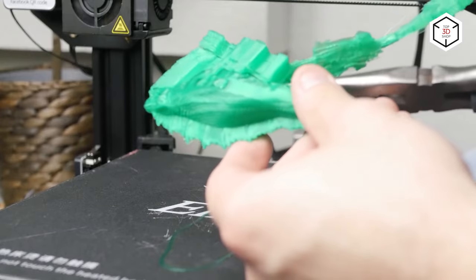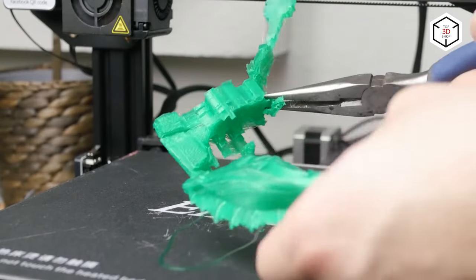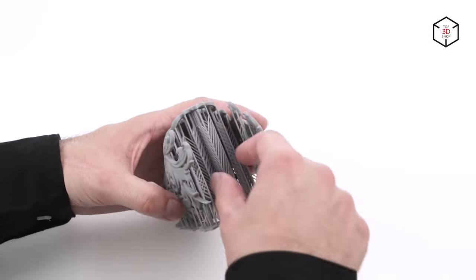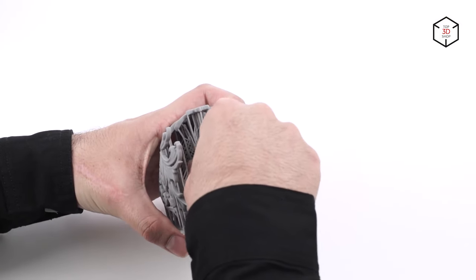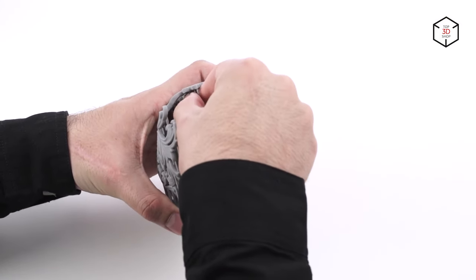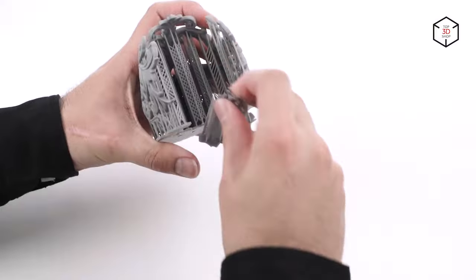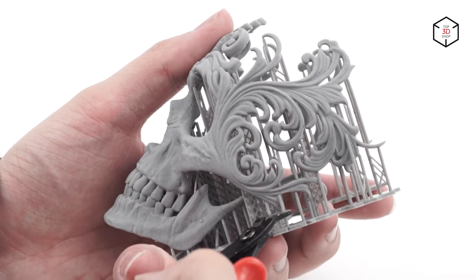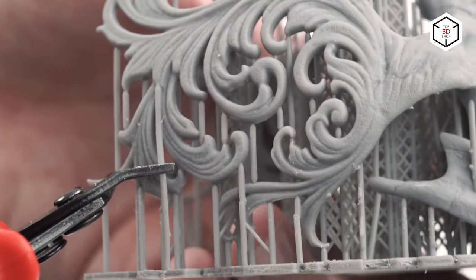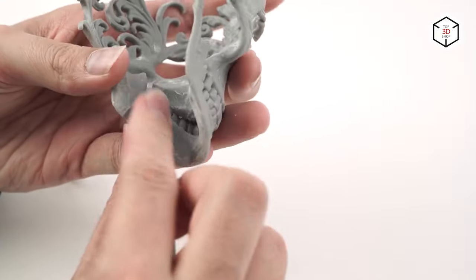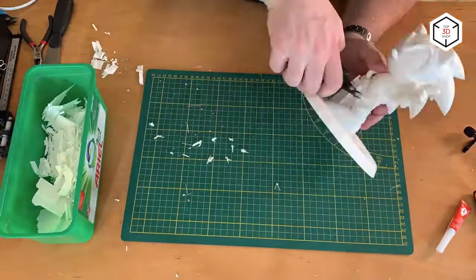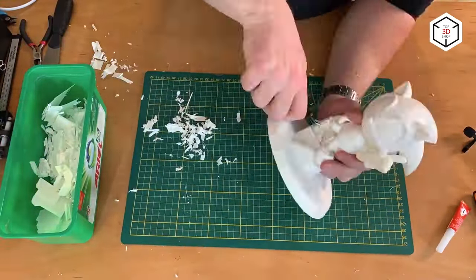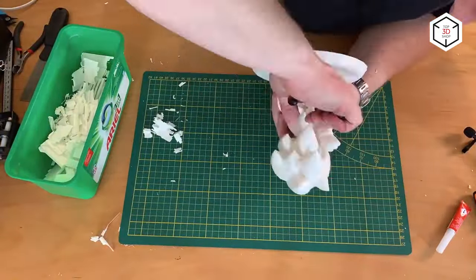Insoluble support structures are made from standard materials such as PLA, ABS, PC, nylon, etc. They are primarily removed by hand, pliers or other similar tools. Nevertheless, there are soluble materials that perfectly fit the role of support structures, such as HIPS and PVA. They greatly facilitate the removal task as they tend to dissolve in limonene and water respectively.